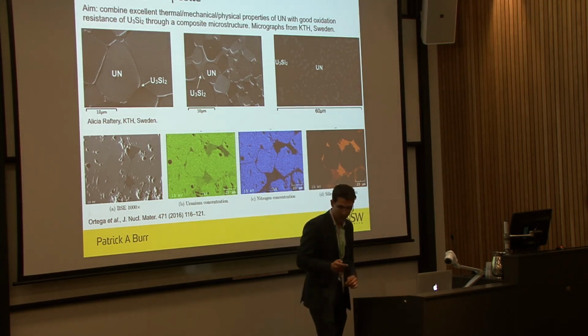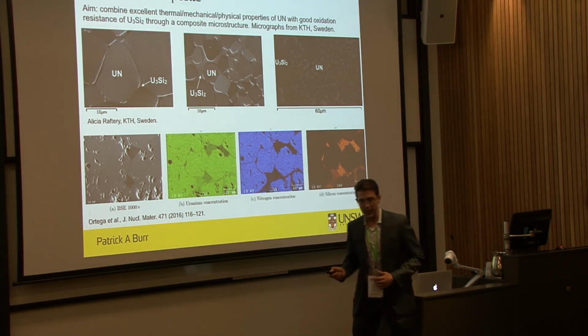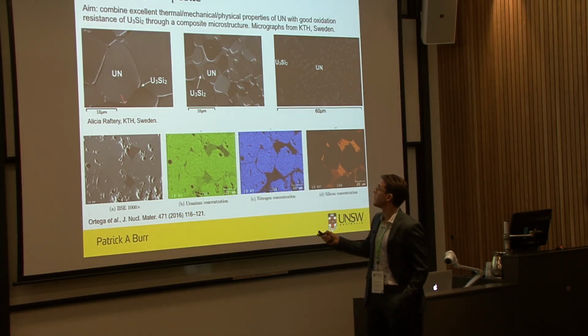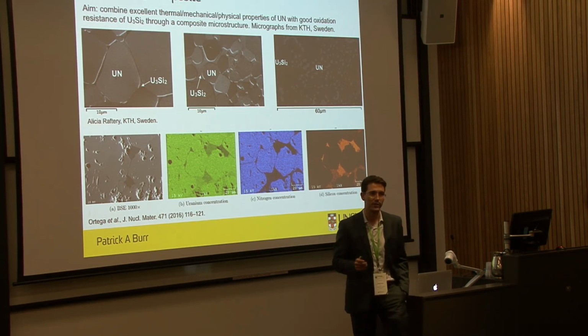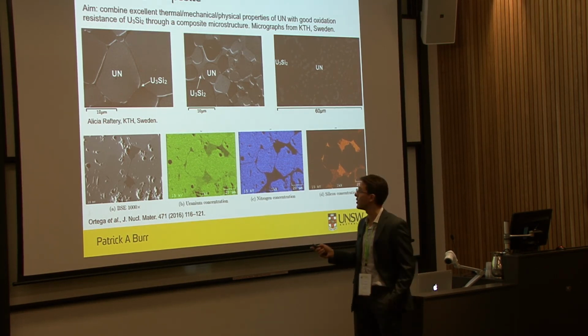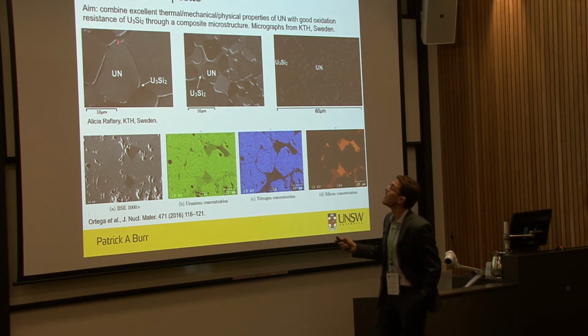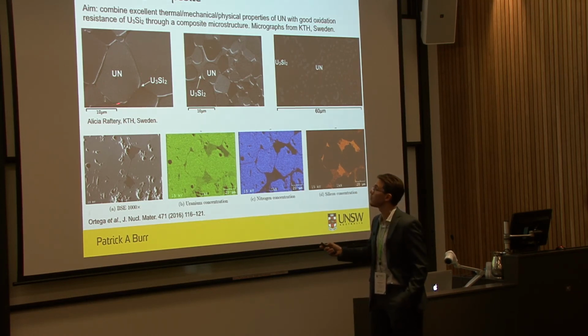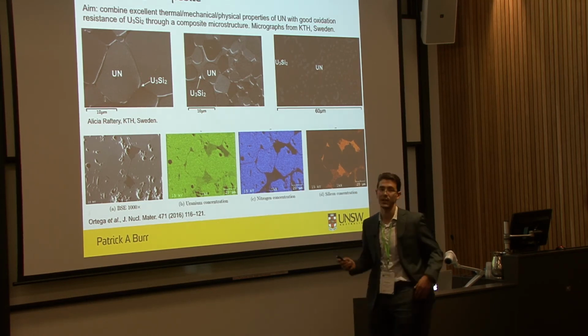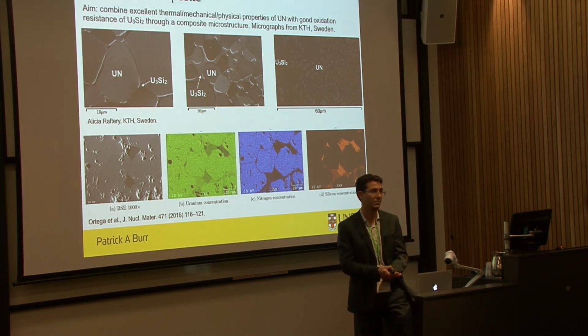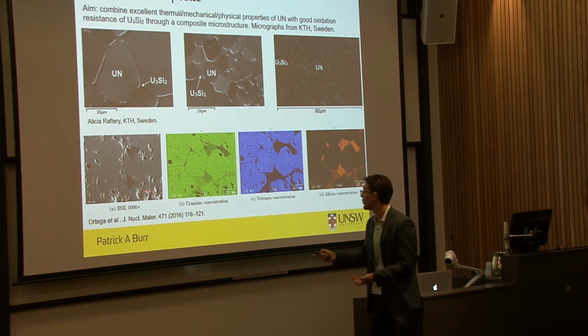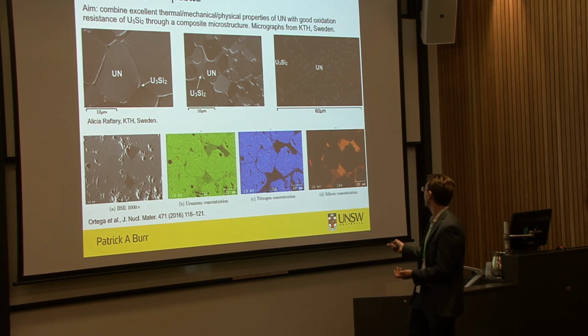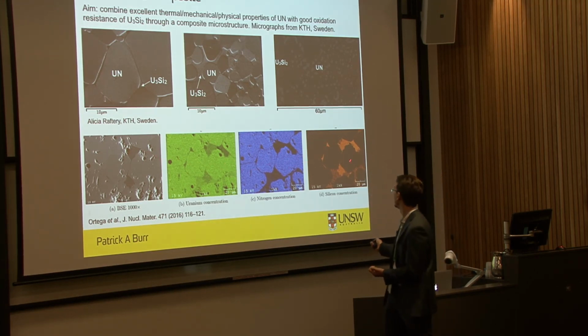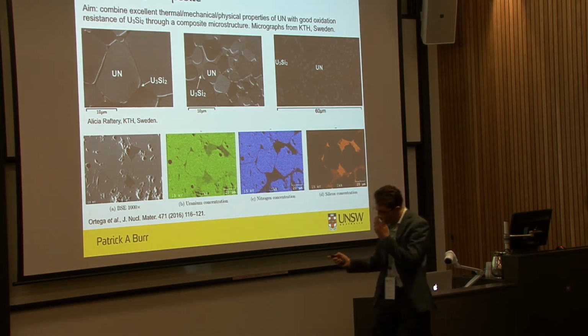I'm conscious of time. We're working with KTH in Sweden and Westinghouse to develop these materials. We're not the first to have come up with this idea, but we believe that KTH are the ones who have done it the best, which is to create uranium nitride surrounded by uranium silicide inside each grain. And that's by spark plasma sintering. This is work showing that this has been done before, but the microstructure wasn't quite as good because you get some ternary phases forming.